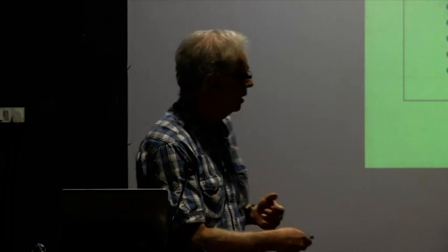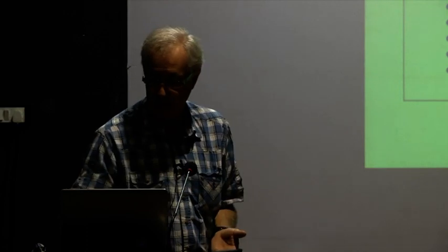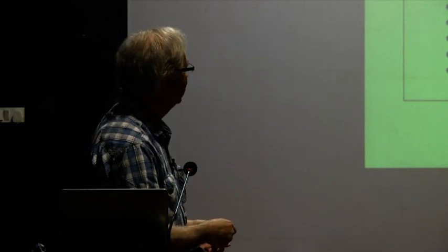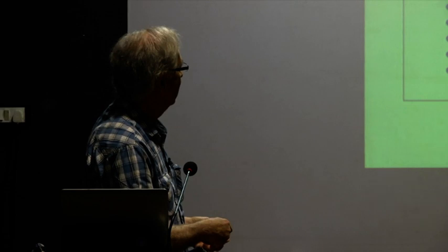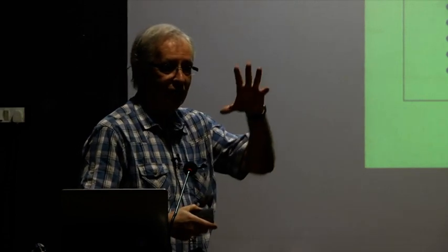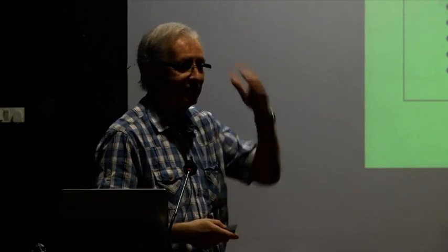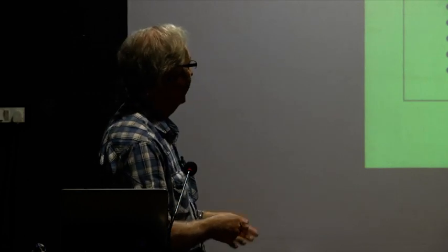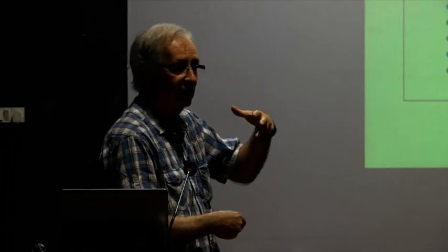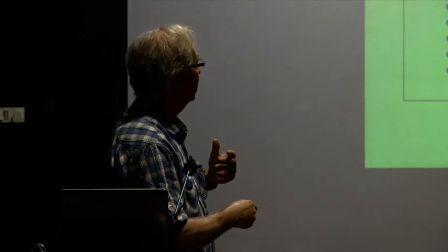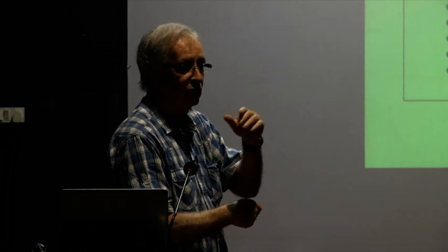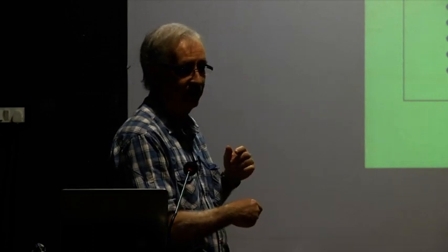And this is what happens. The green is still there. You cool it down. You can apply a magnetic field like this, and what do you see? You see the pulsating thing. So you go from one variant state to the other variant state. You can apply a magnetic field and you can get a strain. Then you can apply a magnetic field to this thing and it will move from one kind of variant to another kind of variant.